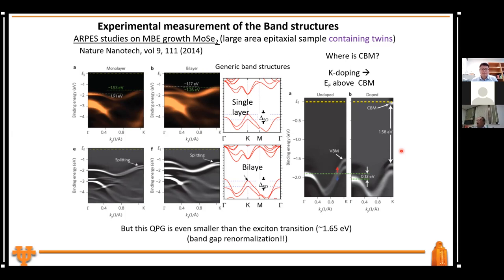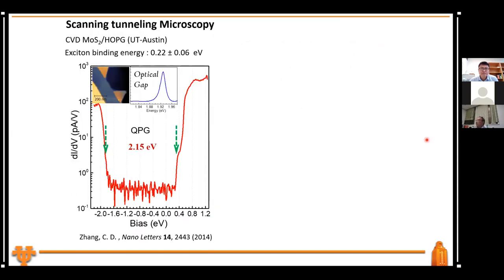Say, well, not only is the exciton binding energy going to be influenced by its environment, the quasi-particle band structure can also be influenced by the environment. And this is what they call the band gap renormalization issue. So this presents some challenge, okay? Now you think about, well, simple.